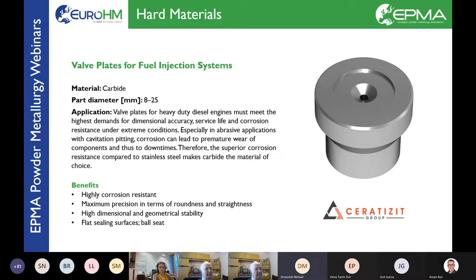The need in that case is for fuel injection systems at heavy duty diesels, that you have to have a high wear resistant material, which has to be very accurate and precise. And on the other hand, in the harsh condition of these fuels it has to have extreme corrosion resistance. And nevertheless, there are still some other impacts like cavitation and the demand of the users that the engines should run all the time, and downtimes are not welcome. Due to this, we have developed this material and these parts together with our customers so that they can run the engines smoothly, even with the worst condition of the fuels used. And that is really a nice example of a corrosion resistant material, which has all the properties needed also in the geometrical capabilities and the other mechanical properties.